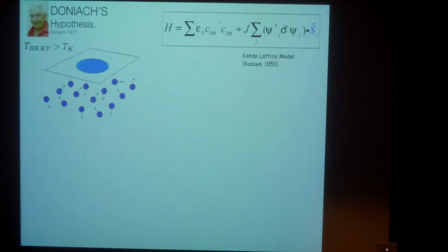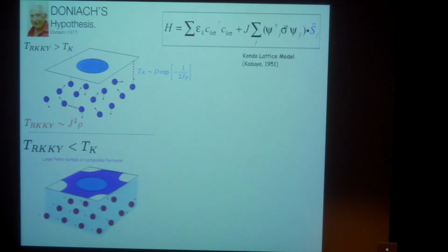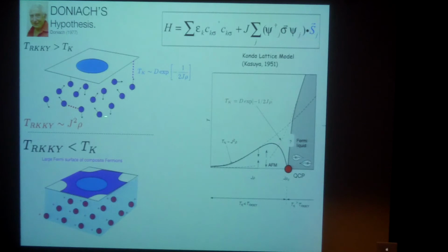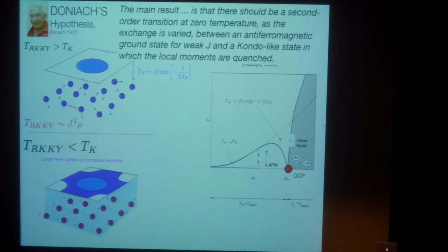So, well, this is one of the things when you embed these local moments in a metallic environment, they start to interact in a new way. And Sebastian Doniach in 1977 pointed out there are 2 interactions that come into play in a lattice: the Kondo temperature, which is this singlet formation scale, and the RKKY scale. And when the RKKY scale is smaller than the Kondo temperature, you can form singlets at every site. And when that does this, the local moments kind of dissolve into the conduction fluid and they become mobile. They form a large Fermi surface of composite fermions. And Doniach realized that in between these 2 extreme limits, you might have a quantum critical point. And that's what he mentioned in his paper of 1977, that second order transition at 0 temperature.